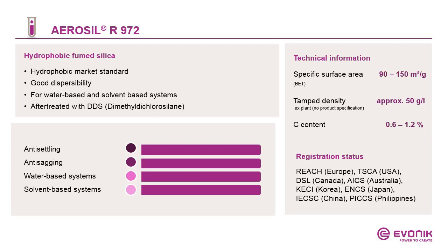Aerosil R972 is our hydrophobic fumed silica market standard. It has good dispersibility, can be used for water-based and solvent-based systems, and its after-treatment is done with dimethyldichlorosilane. It provides a rather low specific surface area of around 120 square meters per gram and delivers optimum anti-settling and anti-sagging properties for water-based and solvent-based systems.